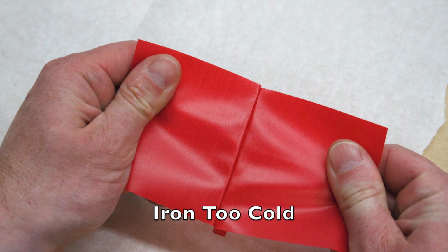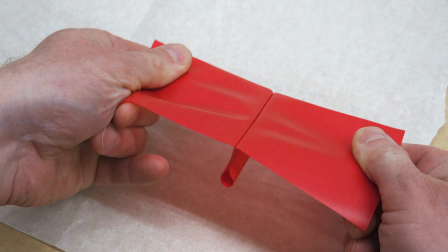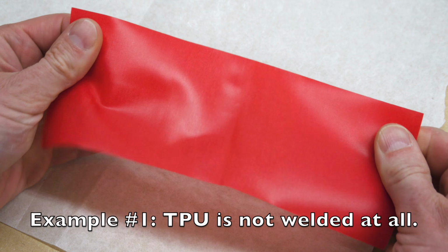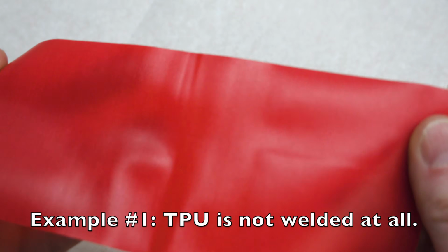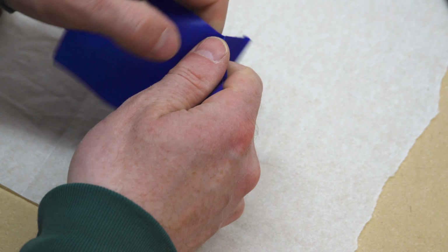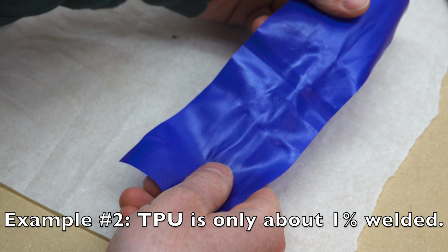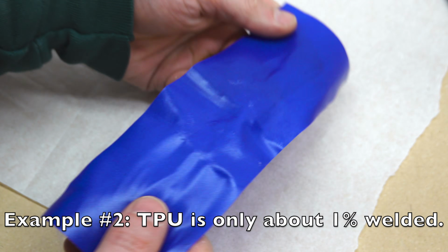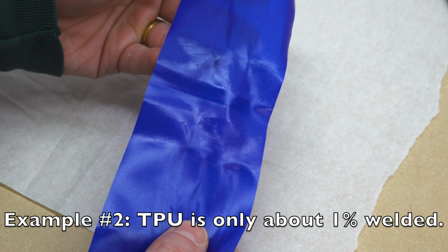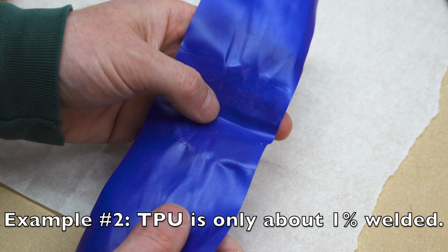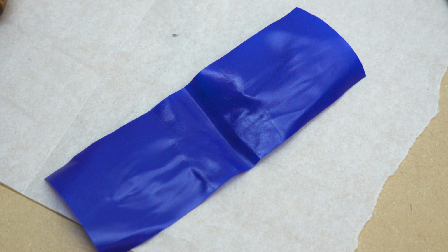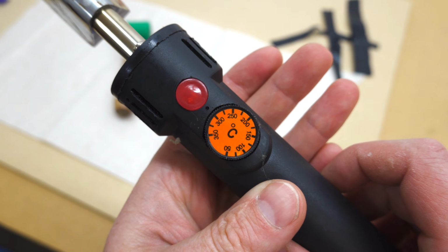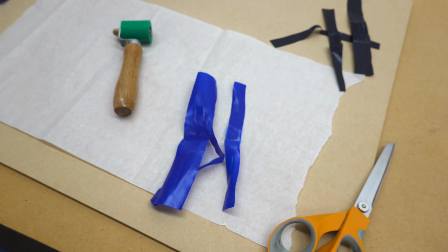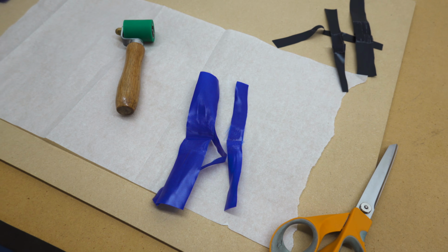So allow it to cool, and then try to peel the fabric pieces apart. We can see here that the fabric pieces are sort of stuck together, but they can be pulled apart without too much effort. The TPU might turn kind of whitish as you force the pieces apart, but if the TPU isn't ripping away from the woven fabric, then the TPU layers haven't fused into a single layer, and it's not a good weld. When the TPU layers can still be separated after ironing, that means we need to raise the iron's temperature.